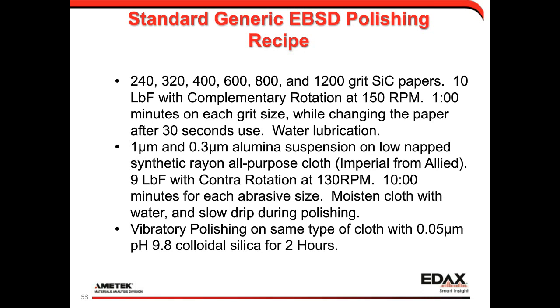The next part, again, is starting with 1 micron and then 0.3 micron alumina suspension on this low nap synthetic rayon all-purpose cloth, which is the Imperial one from Allied High Tech. I go to 9 pounds force, but now I use contra rotation, so the platen and the samples are rotating in opposite directions, at 130 RPM. It should be a little bit more efficient in terms of material removal, but with a lower removal rate due to the smaller abrasive sizes.